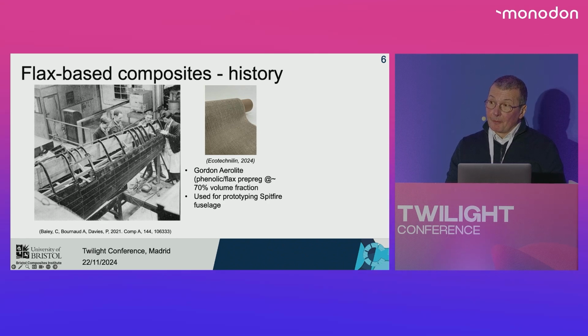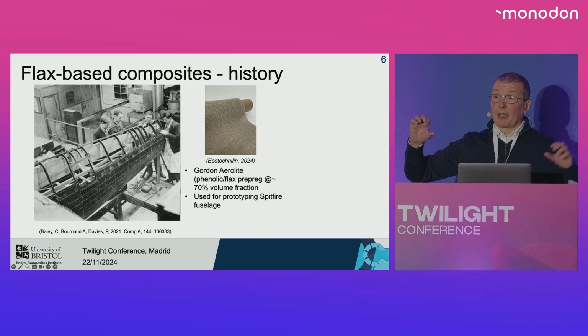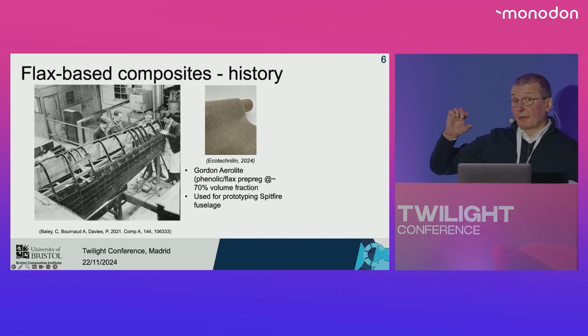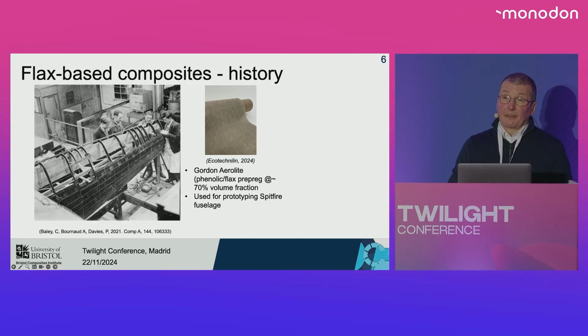Very interesting composites. At the time, they already started to experiment with these thermoforming processes that allowed making composites up to 7 millimeters of thickness. And 7 millimeters of thickness have been only reached recently for carbon epoxy composites, for example, in the wing of the Airbus A350 or similar types of composite. Already at the time they were doing that kind of work.